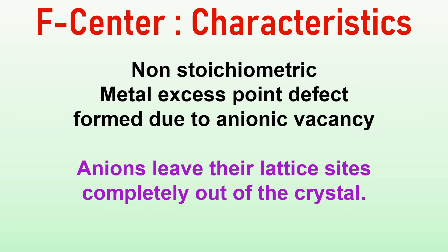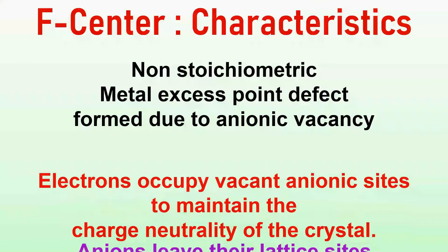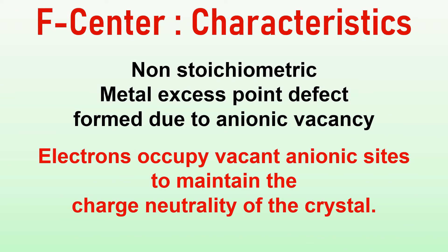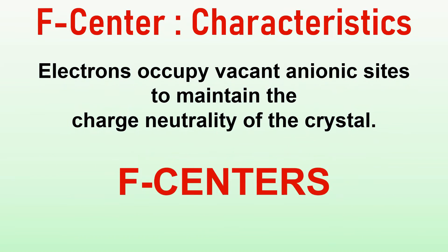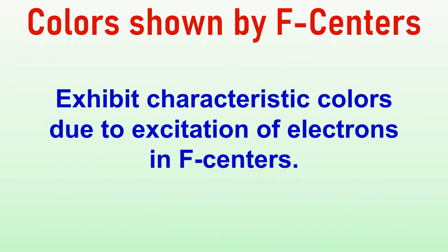Remember that the anions leave their lattice sites completely out of the crystal, and the electrons occupy the vacant anionic sites to maintain the charge neutrality of the crystal. These vacant anionic sites occupied by electrons are known as F-centers, and they exhibit characteristic colours due to excitation of electrons.